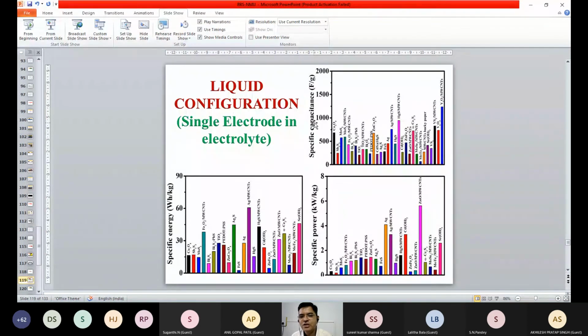So this is specific capacitance, and here you can see that vanadium oxide, vanadium sulfide, and this HgS on the carbon nanotube show the higher specific capacitance. Up till now, vanadium oxide shows the highest capacitance from our laboratory, right? That I have presented. Then for specific energy, silver deposited by electrolysis on the carbon nanotube shows the highest specific energy.